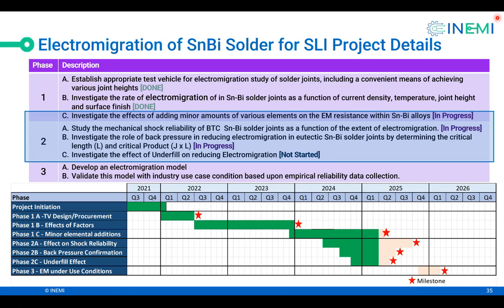In 2B, critical product, current times length, at which there is no electromigration in the tin bismuth solder joints. And C is the underfill effect that has been shown to be a positive one in a couple of presentations, but those were done on the FLI level, not SLI. So we are going to look at the SLI now. And number 3 is the electromigration model that we're going to develop and validate with the industry use conditions.